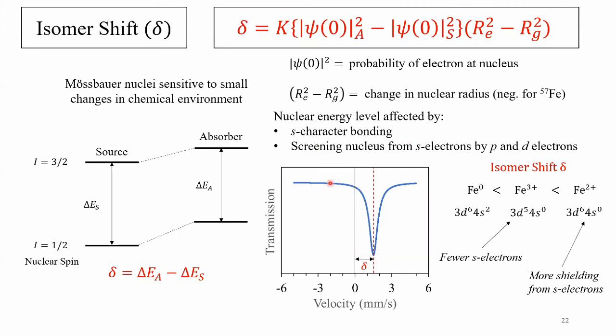So for example, like I said, if you just have metallic iron, it should just be right in the middle with zero energy shift. But if you have iron ions like iron chloride or iron cyanide is my example, then you will expect an isomer shift because you're changing the local environment. And then also screening of the nucleus from P and D electrons. So that has to do with the valence state, right? So if you have metallic iron, you can ionize the iron to iron 3+. So you're removing the S electrons and you have less D electrons. All right, so that screens the S electrons, and that will give you a positive isomer shift. But if you have an iron 2+, you have an even greater positive isomer shift because you have more D electrons to shield the outer S electrons. Anyways,